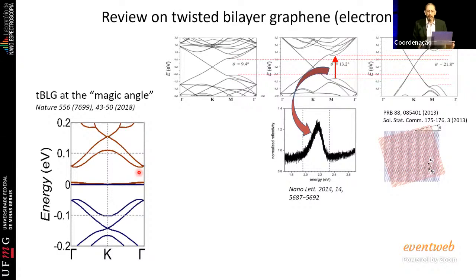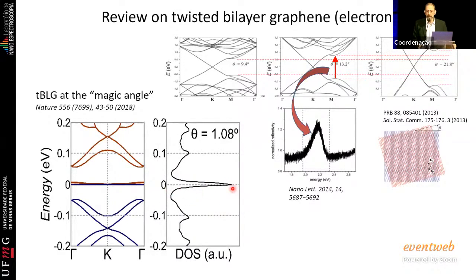But something special happens at this very specific angle, which is the formation of flat bands near the zero energy level. And these flat bands, when you plot the density of states, you will have a high peak of density of electrons at this zero energy, which is where transport usually happens, where excited electrons will transport current and all these things. So at this very specific magic angle is where graphene becomes a superconductor and exhibits other very interesting correlation phenomena, correlation of electrons, phonons, and electron-phonons.